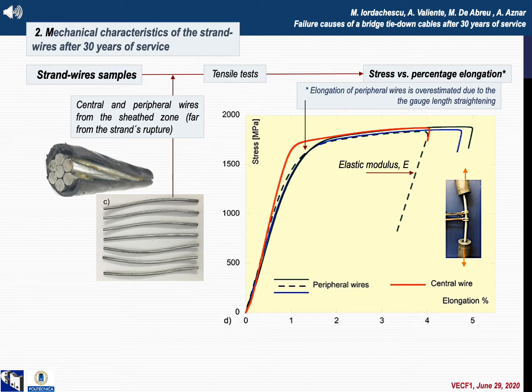In contrast, the elastic load slopes are appreciably lower, of order of 150 gigapascals, excepting that of the central wire of 200 gigapascals. The peripheral wires bending during testing explains their higher deformability. The percentage elongation under maximum load exceeds, in all cases, 3.5% required by the standards, but its dispersion suggests that two of the specimens have lost part of their ductility before testing by previous plastic deformation and strain hardening during the service failure.